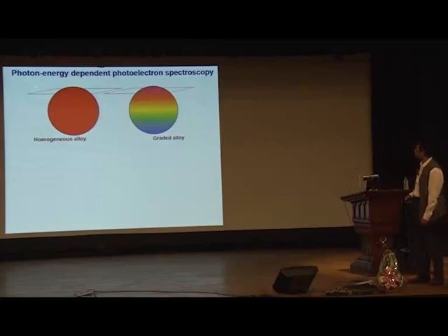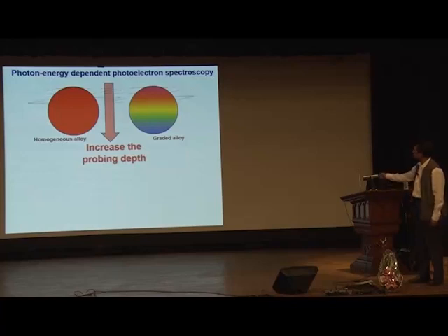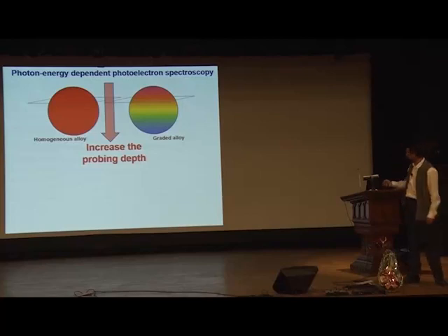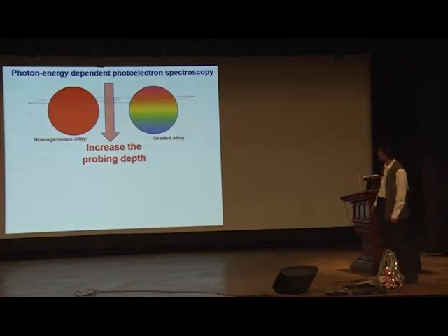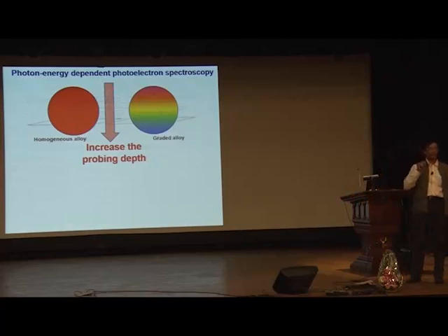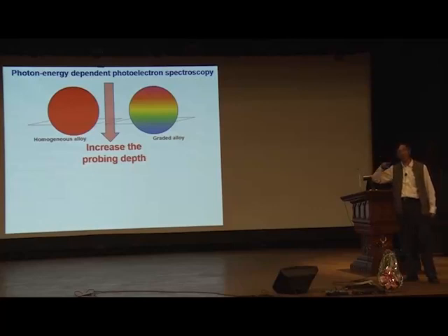So what I'll do is stepwise increase my photon energy, and I'll go to that step. And the differential between these two steps that I showed, if the escape depth controls in a rectangular fashion rather than the exponential fashion, then between this previous step and this step, if I take the difference of the spectrum, I get exact composition within that slice. I can go on doing this as much as I want. And since the photon energy can be changed by any small arbitrary amount, I can make these slices as thin as I want in principle and exquisitely map out exactly how the composition varies.